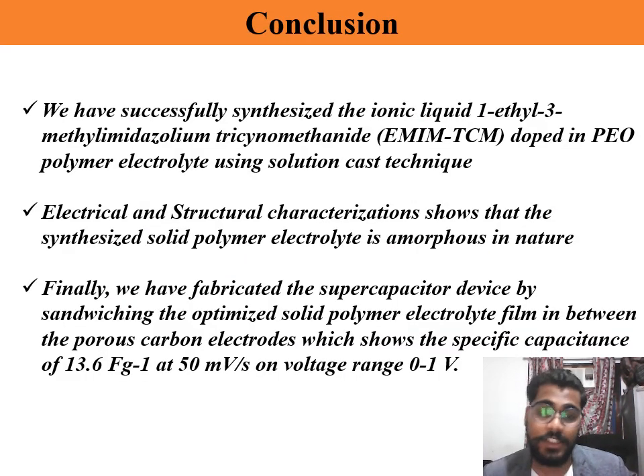Next, we have finally the conclusion part, where we have successfully synthesized the ionic liquid 1-ethyl-3-methylimidazolium tricyanomethanide doped in a PEO polymer electrolyte using solution cast technique. The electrical and the structural characterization shows that the synthesized polymer electrolyte is amorphous in nature. Finally, we have fabricated the supercapacitor device by sandwiching the optimized solid polymer electrolyte film in between the porous carbon electrodes, which shows the specific capacitance of 13.6 farad per gram at 50 millivolt per second on a voltage range of 0 to 1 volt.